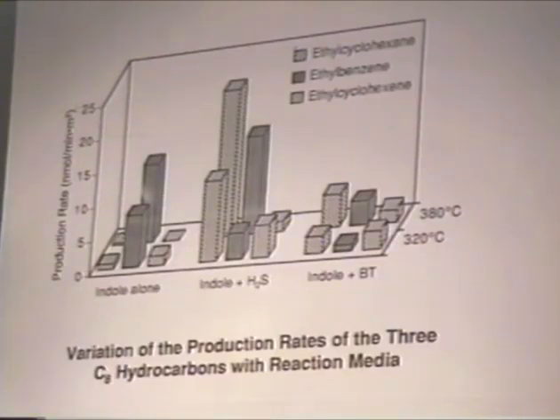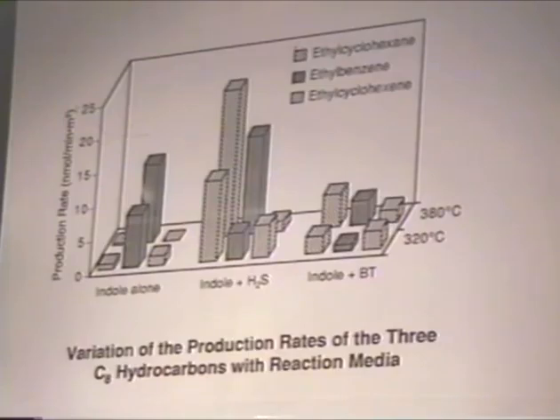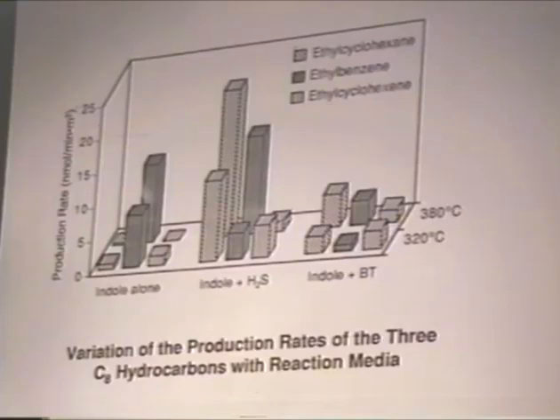Now, if we compare the three C8 hydrocarbons, which are the main hydrocarbon products that we observe, namely ethyl cyclohexane, ethyl benzene, and ethyl cyclohexene, what we see here is when we have only indole, ethyl benzene is the major product. When we have sulfur compounds present, some of the completely hydrogenated or partially hydrogenated products become important, namely ethyl cyclohexane in this case, and both ethyl cyclohexane and ethyl cyclohexene actually in both cases.